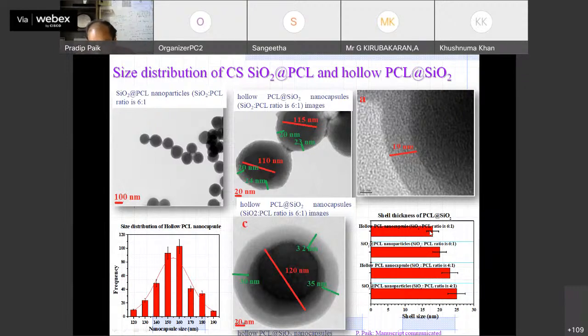So if you take different ratios of whatever I told, you can take the polymers, inorganic nanoparticles. Instead of silica, you can take everything: iron, gold, silver, any type of inorganic. Actually a solid core always helps to make a concrete structure, and it is sometimes easy to remove. By etching with sodium hydroxide or HF, hydrofluoric acid, you can remove these things.